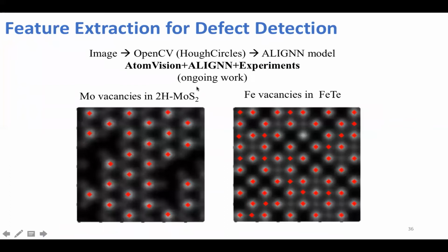In addition to classification, we can use feature extraction and semantic image segmentation applications. Here's an example for Mo vacancy in MoS2 and iron vacancy in telluride. We can detect where the atoms are using something like Hough circles or some other models, and then construct an atomistic line graph, similar to what we described in the earlier model, and predict properties directly. That will be very useful for the experimentalist, I believe, because our huge DFT data set will no longer be standalone in its own world.